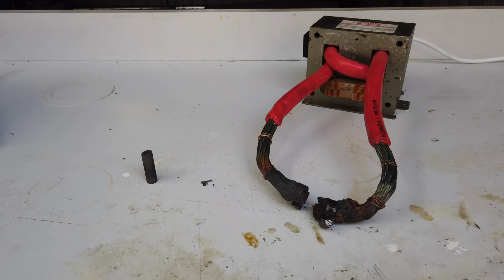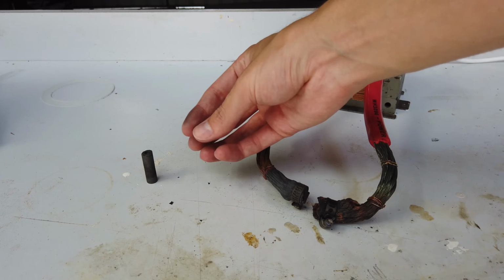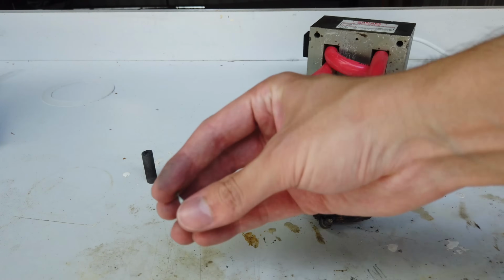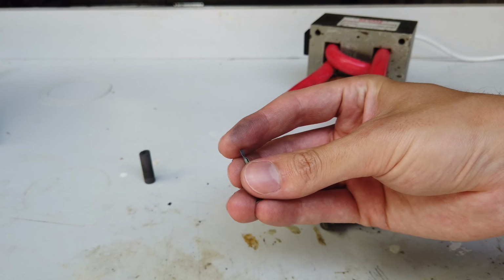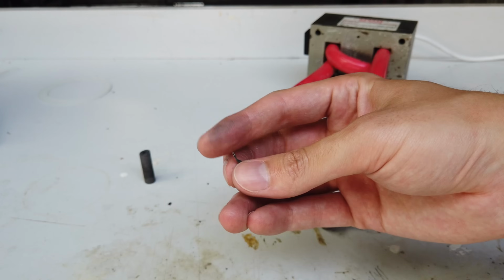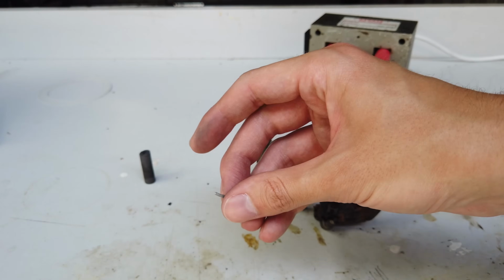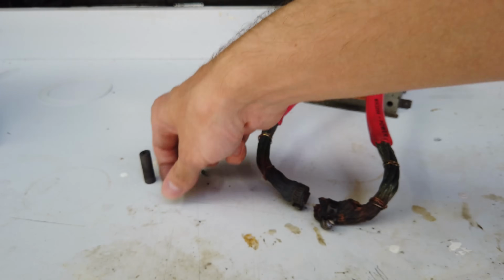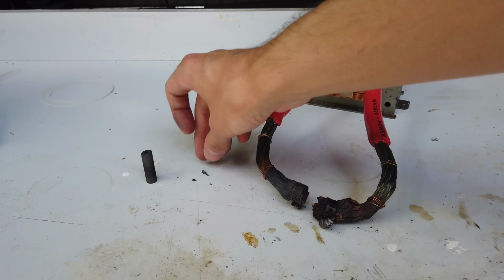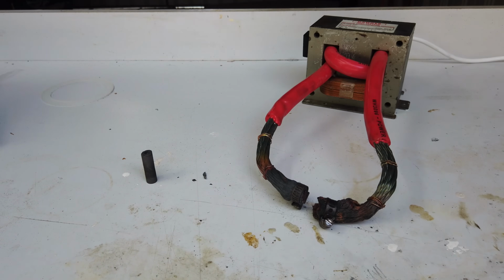Slightly disappointing result. We were not able to actually melt our titanium foil. You can see here, the titanium foil is still intact. It got significantly more brittle and a bunch of it kind of fell to pieces, but we did not melt the metal.